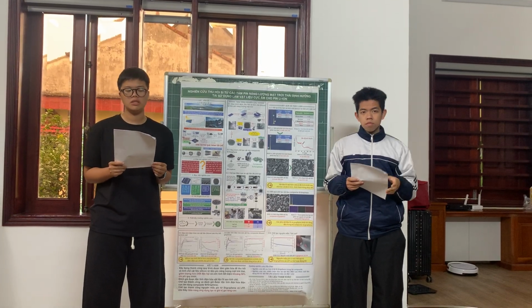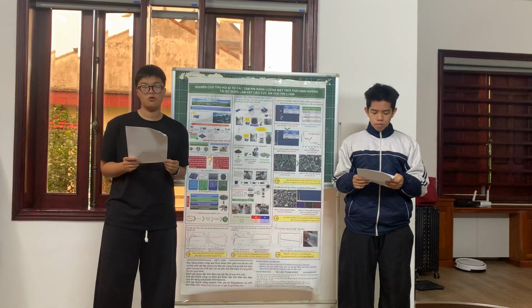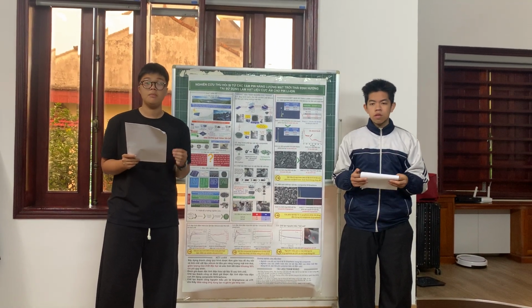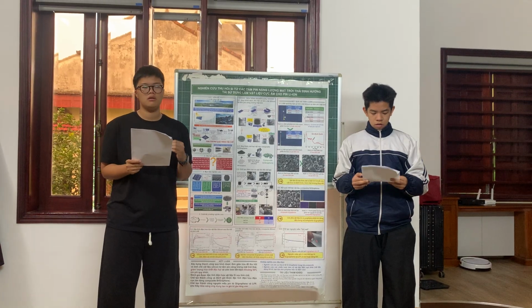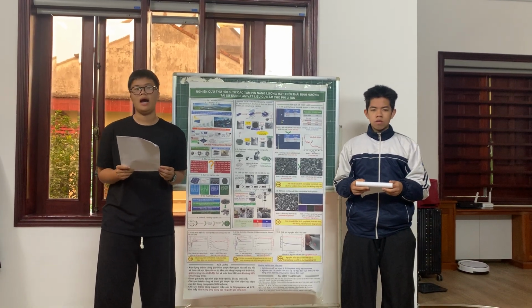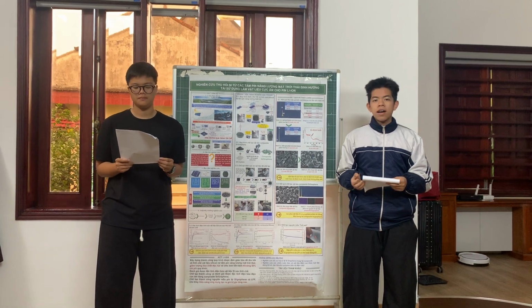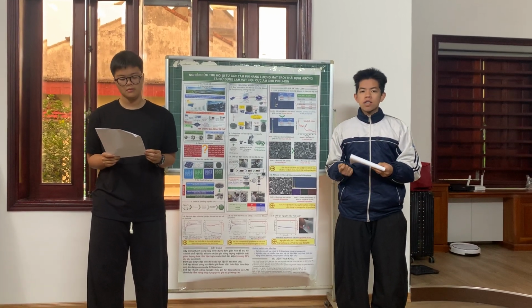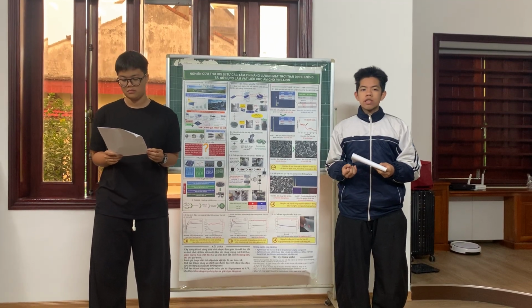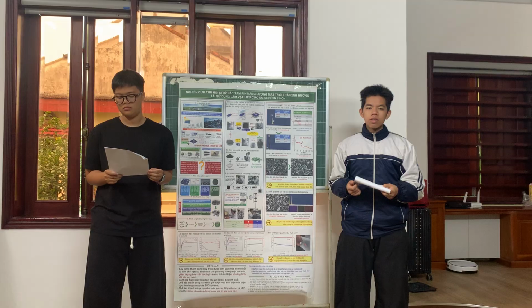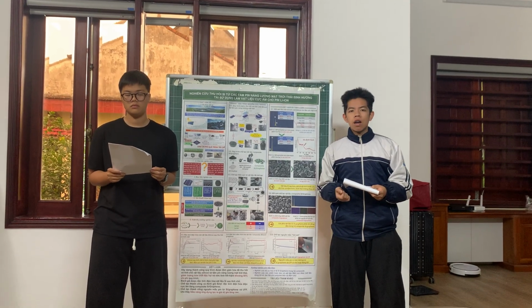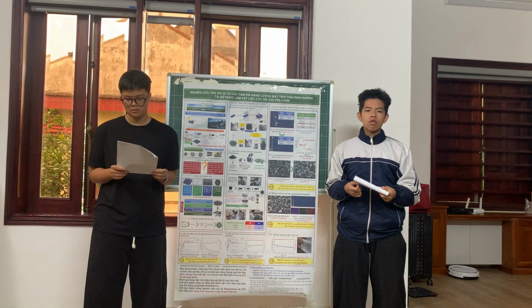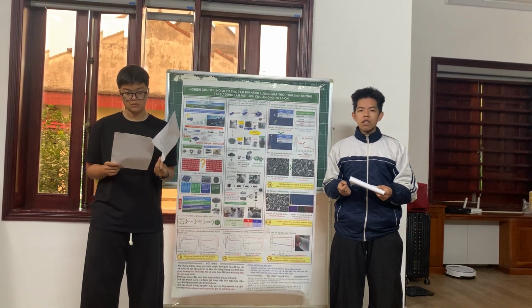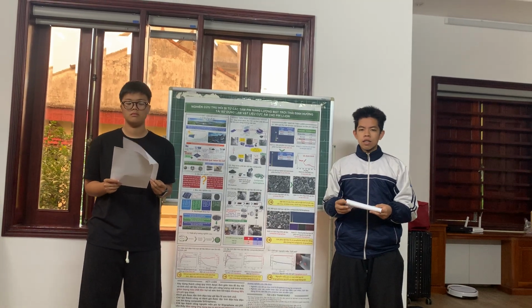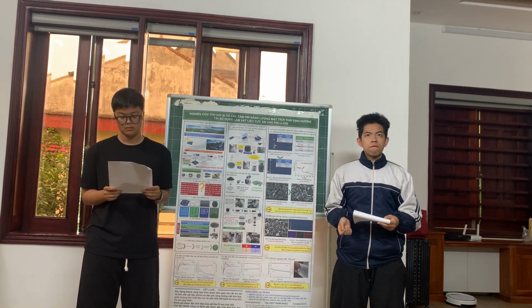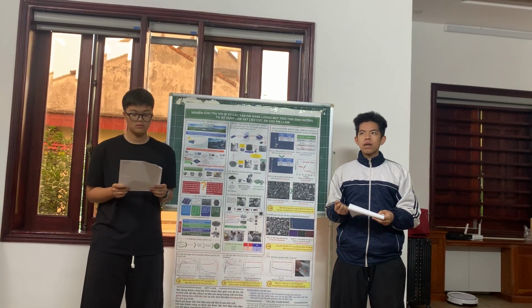Drawing from this practical background, our group has chosen the topic: research on the recovery of silicon from decommissioned solar panels for repurposing as anode material in lithium-ion batteries. The main focus of this project is to exploit the potential of silicon as a high-performance anode material. Despite high capacity, silicon suffers from severe volume expansion during lithiation, which leads to structural collapse and rapid capacity fading. To address this issue, graphene, a low-dimensional material with superior electrical conductivity and excellent mechanical properties, was introduced to enhance the electrode durability.